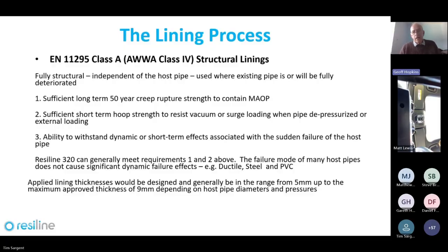We wouldn't make that claim for cast iron pipelines because the failure mode tends to make the lining fail as well. But ductile steel and PVC we're okay with. Lining thicknesses would generally be from 5mm up to our maximum of 9mm. But we don't really tend to look at that too much, because you probably find it's cheaper to lay a new pipe than put 9mm, or our NSF approvals up to 14mm. It's not really cost effective. You're moving out of where we can really compete against other techniques if you want to put fully structural linings in.